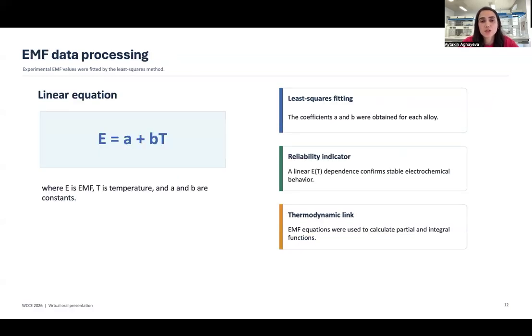The experimental EMF values were processed using the least squares method. The temperature dependence of EMF was described by a linear equation, E equals a plus bT. Here E is the electromotive force, T is temperature, and a and b are constants. For each alloy, the coefficients a and b were calculated from experimental data. A linear dependence of E on temperature is an important reliability indicator. It shows that the electrochemical cells work stably and reversibly in the selected temperature range. After obtaining the EMF equations, they were used to calculate thermodynamic functions.